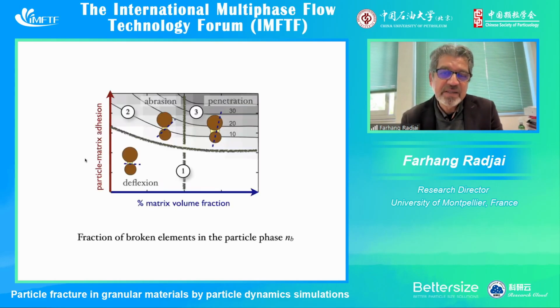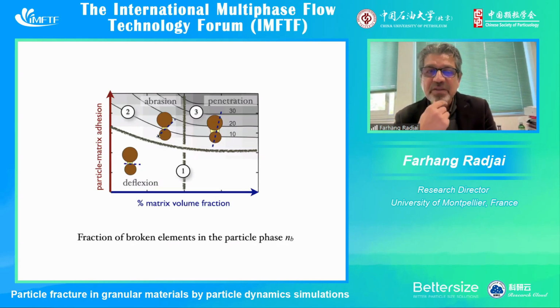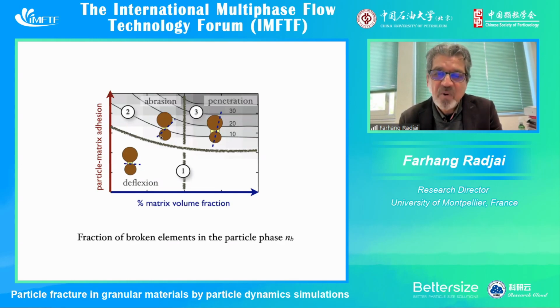The second interesting result is that if we look at the fraction of broken particles in this space, we see that we can differentiate different crack propagation patterns. So when we have, for example, low matrix volume fraction and low adhesion, then most of the time the cracks propagate bypassing the particles. They propagate only in the binding matrix. But when one of these two is high, for example, even at low volume fraction of the binding matrix, if the adhesion is high, we get abrasion. So the cracks can also propagate into the particle, but they only chip the particle. They only break the particles at the surface, they don't go deep inside the particles. And when both are high, we have crack propagation through both the binding matrix and the particles.